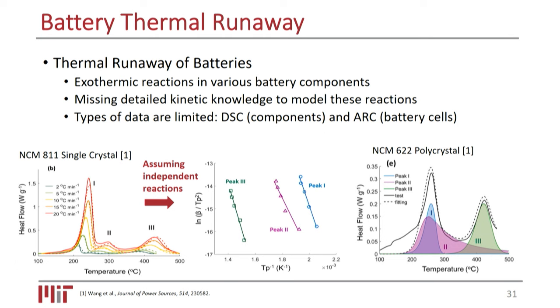This is another NCM material with slightly different composition and crystal structure. You actually only see two peaks, the dashed lines here. But you know, it's the same material, so it should have three reactions that are giving away heat. Then how do we assign peaks? So actually, when you do DSC analysis, the software can do it for you.